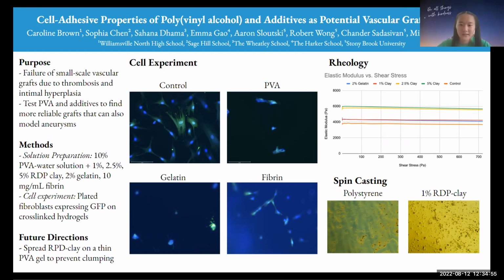So these images in the center look pretty similar across days, but these are all from day 1. On the top left, where cells were plated directly onto the well plate, there is a really high cell density and many cell connections. The top right PVA-only gel has more circular cells with smaller cell connections, and the bottom left gelatin gel is insignificantly different from the PVA-only gel. And the bottom right fibrin gel has higher density and longer cell connections, which is a promising result. The RDP clay gels showed no growth, so the oven-heated clay may have killed the cells.